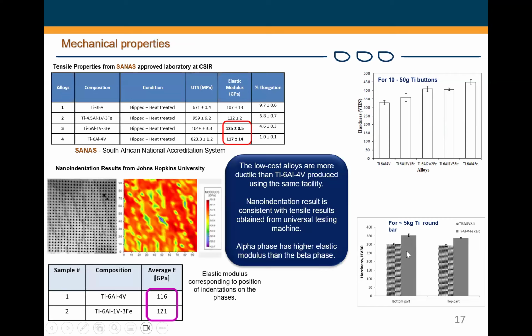We were able to carry out tensile tests, because now we have samples that are big enough to machine tensile samples, and we were able to gather the result that I'm showing you in this table. And I mean, the CSIR lab is a SANAS approved laboratory. And we didn't end here. We sent the sample to Johns Hopkins University for nano-indentation results, just to validate what we've done at CSIR. And you can see that in terms of the elastic modulus of both alloys, they're very, very close. This is the same samples we produced here, tested in South Africa and also analyzed in the US, and we got similar results. So we have confidence that the alloys are really good.